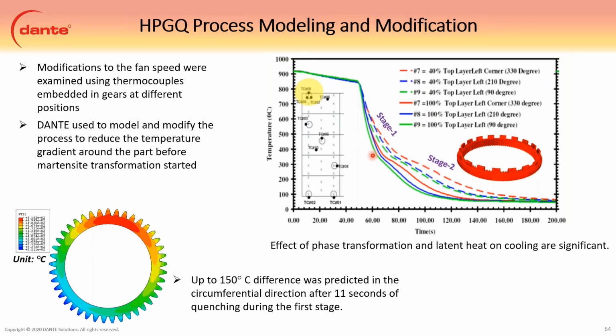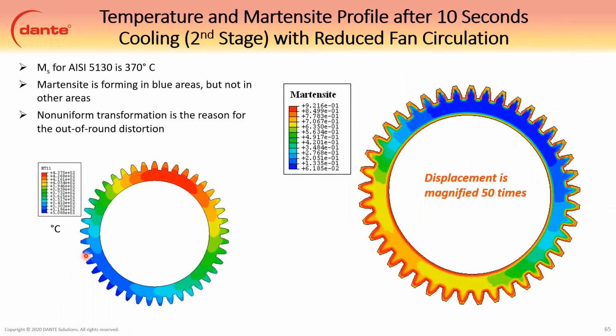You can see a couple of the experiments that we ran, but these are differences around the ring itself. So there was a lot of temperature non-uniformity going on here. And you can see in the figure on the bottom left from the simulation that there's up to 150 degrees Celsius difference within the ring, which leads to significant distortion, because your martensite transformation is starting over here and is like 70% complete over here in the core, where over here it's 0. This little bit around the outside is insignificant to the overall distortion. It's this bulk core material that's going to drive the major distortion.